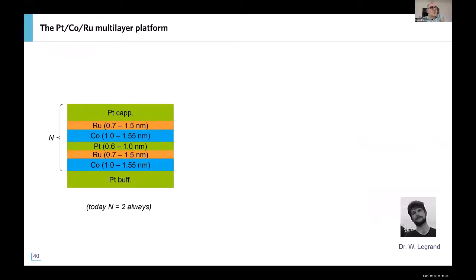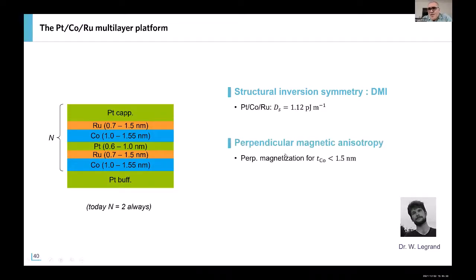Then I talked about the ferrimagnetic system, but we also had some work on the antiferromagnetic systems, and it was in the PhD work of William Legrand. And for that, we use the platinum cobalt ruthenium platform. These are the typical stacking of materials that we use. And because we can prepare with this system a multilayer with a very large Dzyaloshinskii-Moriya interaction that is needed again for all these chiral objects, we can precisely control the perpendicular anisotropy.